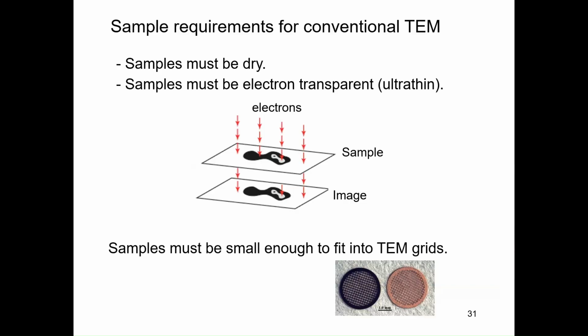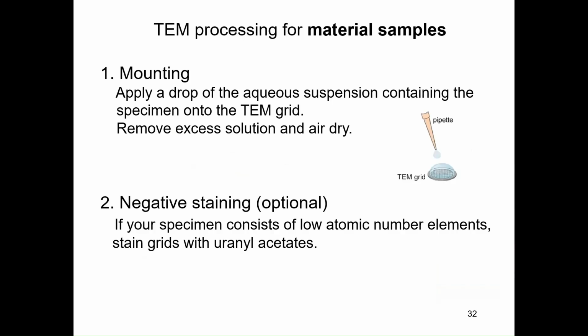And another requirement would be samples must be small enough to fit into TEM grids, which is 3 millimeter diameter. So if you have samples in a suspension in a liquid, then we can just put a drop of your samples and let it dry, and we can put it in a TEM. Or if your samples are not electron dense, then we have to stain them using uranyl acetate. It can give the electron density, then we can see samples.